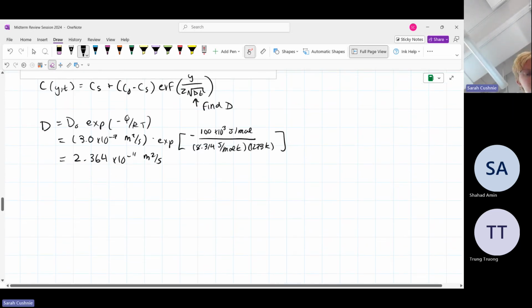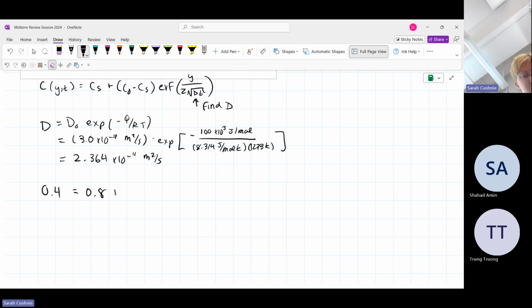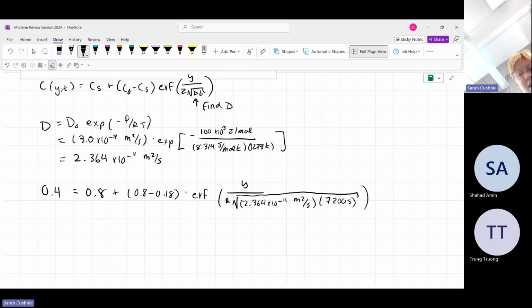So the concentration we're looking for is 0.4, and that's going to be equal to the surface concentration, which was 0.8, plus 0.8 minus 0.18 times the error function of Y, because again, we don't know that depth, over 2 times the square root of 2.364 times 10 to the negative 11 meters squared per second times 7,200 seconds. Again, we need to make sure we're in SI units here, because if we put in hours there, we're going to get a totally wrong answer.